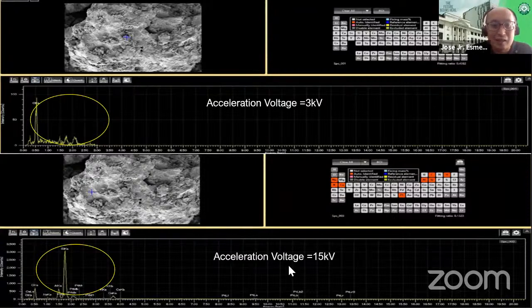So what does this overvoltage affect? You can see from here, if I use only 3 kV acceleration voltage, at a certain point I see fewer elements. It's barely possible to identify what these are. In the periodic table, you won't see anything at all. If I increase the acceleration voltage to 15 kV, on the same material you can see a lot of elements sprouting out from the spectrum. You can identify a lot of elements. It can even see the sputter coating on that material, the platinum. So that's the difference between the two acceleration voltages. That's what the overvoltage ratio does.